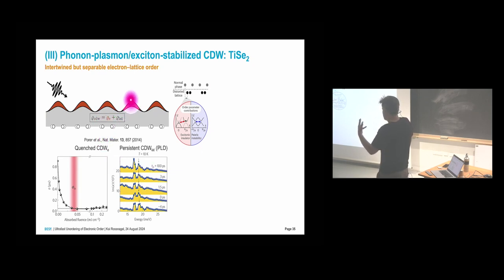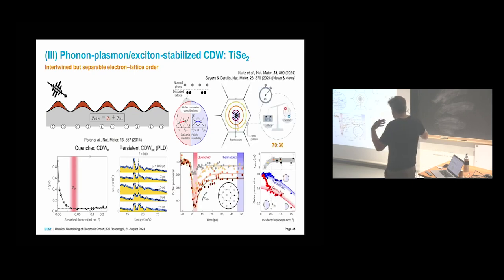So you can have, in this scenario, a state where you can quench this electronic component very fast. So this is indicated here at a critical fluence. You have the scattering rates of the normal phase. So you have quenched the electronic correlations, but still you see the relevant phonon mode. So the lattice distortion is still there. Yeah, so quenched electronic distortions, persistent lattice distortion. This you can have in this split scenario in the excitonic insulator instability, and these results are a strong indicator that this is really true.